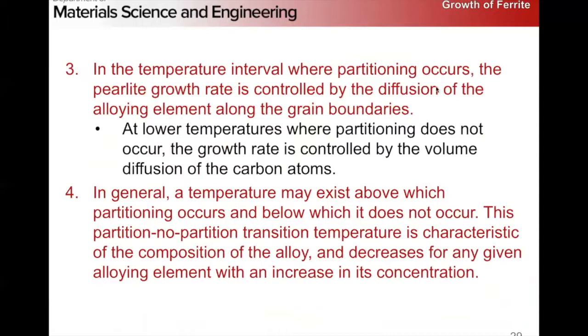In the temperature interval where the solute partitioning occurs, the pearlite growth rate is controlled by the diffusion of the alloying elements along the grain boundaries, right? It's mostly occurring by grain boundary diffusion, not by bulk diffusion.